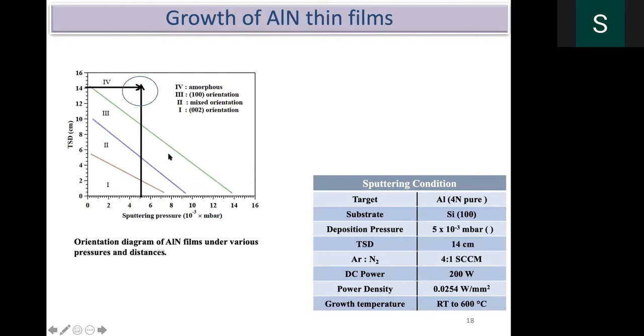But practically, no one has shown a precise one, which in the future course I will show you how we have grown. And if you grow a film in region 2, there is mixed orientation. Always this you can get. 100 and 002 both will coexist normally. If you go below 6 centimeters in distance, then you will get a 002 orientation, which people have already deposited and demonstrated very well.